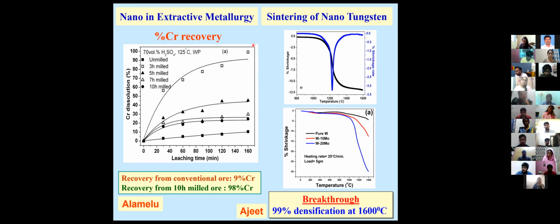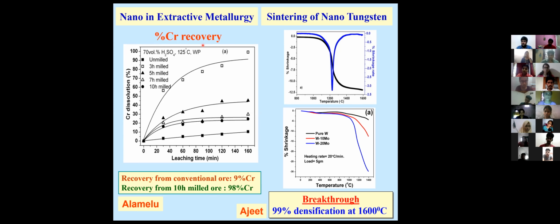When you want to extract metal out of an ore, we simply take the ore and put it into a ball mill like this, make the powder particle size extremely small, and use what is called an acid leaching technique. Typically, if I use the acid leaching technique on powder particles of the size that you see in, let's say, Marina Beach, you get a metal recovery of 10%. But I simply take the Marina Beach sand and convert it into a much finer size by 2 or 3 hours of ball milling, and I get a recovery of metals by a similar acid leaching technique of almost 100%. From 10% recovery, I go to 100% recovery. This is just because I'm enlarging the surface area so that the material can easily react with others. Okay. Similarly, we can also utilize this large surface area for what is called sintering.